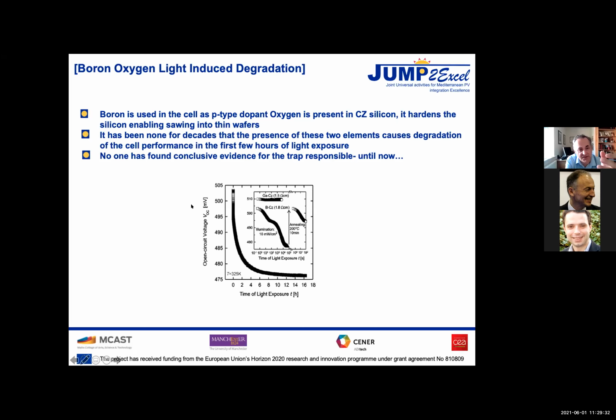Within a few hours, its efficiency drops by typically something like 5 to 10% relative. So a cell that might be 23% will go down to 21% after it's been exposed to sunlight for a few hours. And as I say, it's been known about for 40 years, and there's lots of behavioral information, which you can see here. This is a result from Brett Hallam.